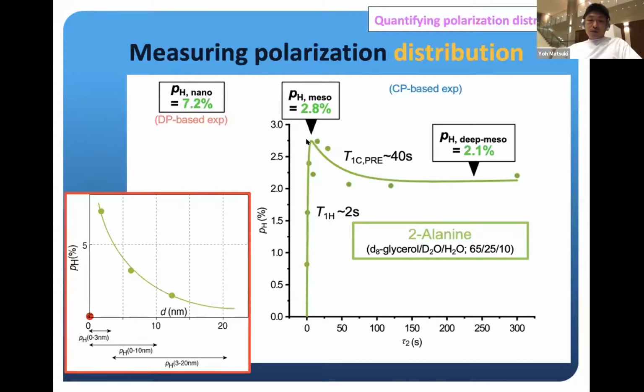So with this model, this experimental tau2 dependence, which has this particular shape here, can be interpreted as right after proton T1 in several seconds in tau2, the polarization level within mesospace is observed. Then later on, after this slow decay due to the PRE, the deep mesospace polarization is observed. Together with the nanospace polarization measured with the DP-based experiment, you clearly see this very steep polarization gradient that's set up around the radical molecule. The sample was alanine in highly deuterated DNP juice.